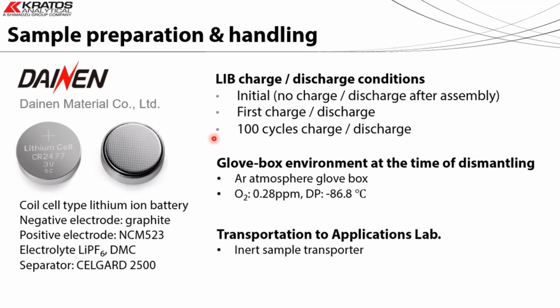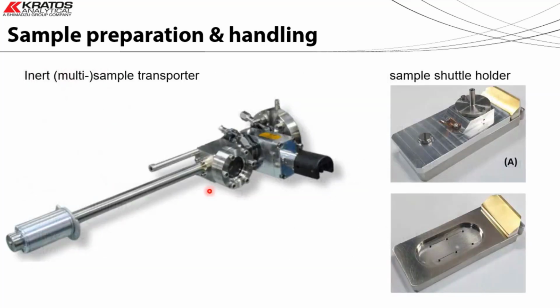And as we're aware, these types of samples are very atmospheric sensitive. So the sample preparation was done in a very environmentally controlled glove box. Now that happened at Dainen's lab, and the samples were transported to Kratos using an inert sample transporter. There was quite a large physical distance between the 2 labs in Kyoto.